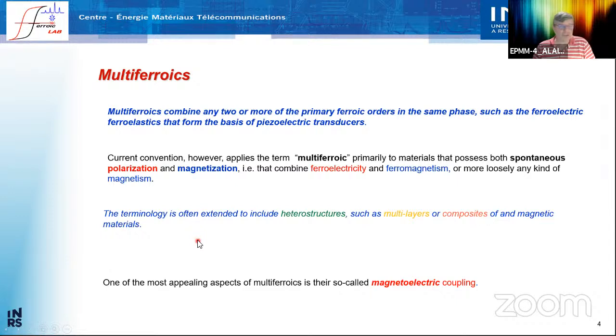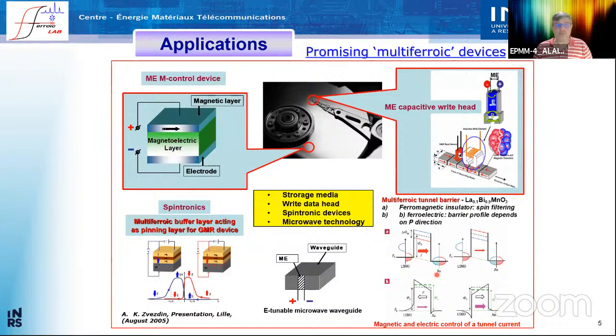One interesting property of the multiferroics is the coupling between those two order parameters. So the coupling between polarization and magnetization. This coupling is called the magnetoelectric coupling, which means that you could control or manipulate the magnetization with an electric field, or vice versa, control the polarization with a magnetic field, which is actually what makes these materials most interesting for application. And there is quite a lot of promising applications which have been already devised.